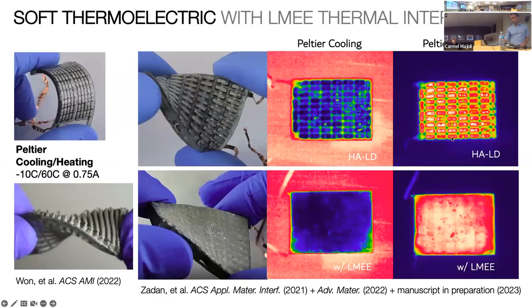This is something that we haven't published yet, and unfortunately, I don't have a scale bar, so you can't see what these temperatures correspond to. But we can get down to, I forget off the top of my head whether it's 5 degrees C or 10 degrees C, but it's a very noticeable cooling. The performance that we're getting with these soft thermoelectrics is equivalent to the rigid thermoelectric devices, but the fact that it's soft means you can have very intimate contact with the skin, so you'll get much more of that cooling sensation. I see the survival suit of the future. That's right, yeah. Post-apocalyptic future, right?